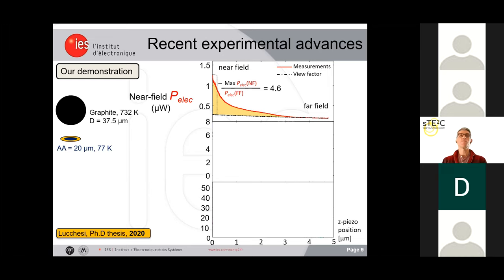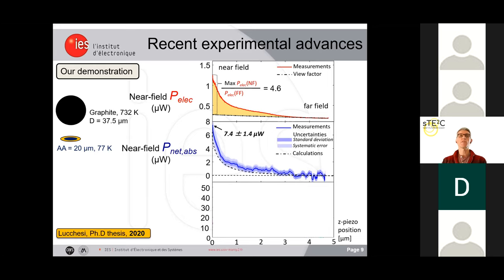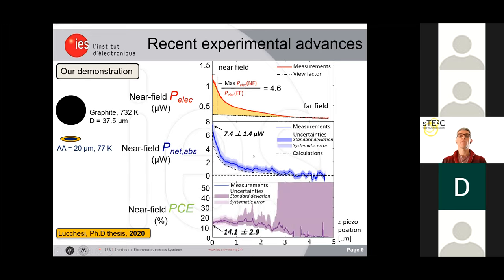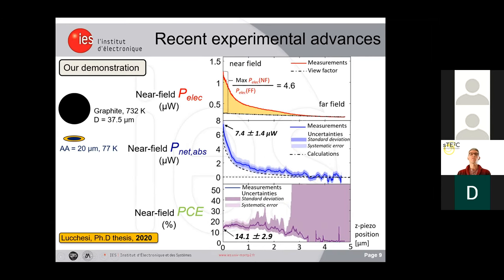As I told you before, it is possible to measure at the same time the net radiation power absorbed as a function of distance. And we see that the measurements compare very well with calculations. And with these two measurements, by making the ratio, it is possible to determine the near field power conversion efficiency, which in this case, at the minimum distance, reaches 14%.